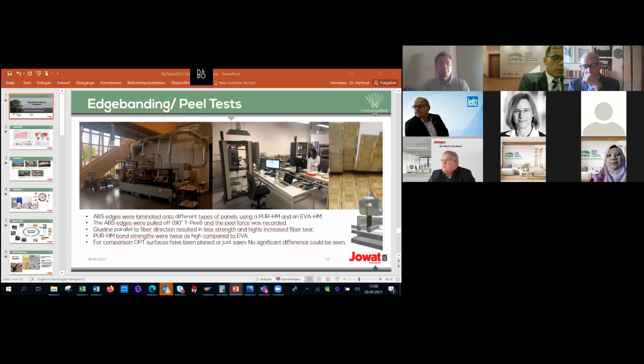But what does it mean to the strength? We tested it with the EVA hot melt and the polyurethane hot melt edge bending adhesives. And the polyurethane was always about twice as strong as the EVA. Both were okay. So it was no problem with the strength, a little lower limit than with, for example, particle board, but still very good results.